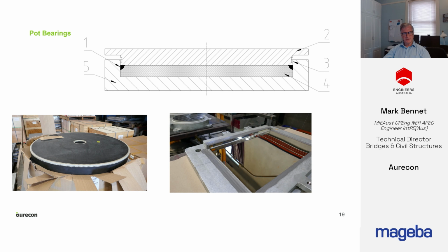Another interesting feature is that where you have a sliding interface using a polished stainless steel sheet, it should be welded to the backing plate to prevent interface corrosion. Unfortunately, in years past, stainless steel sliding sheets were just attached using countersunk screws, and there's lots of bearings with very bad interface corrosion occurring.